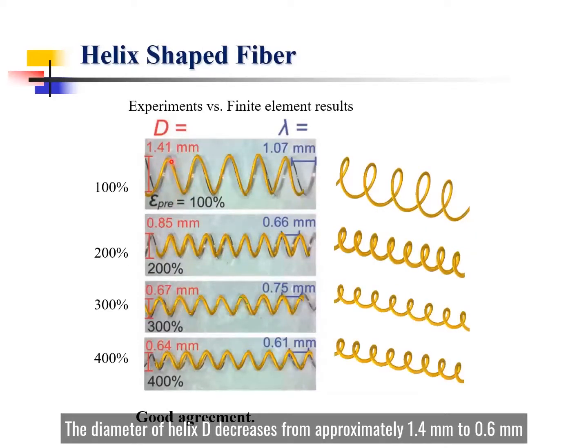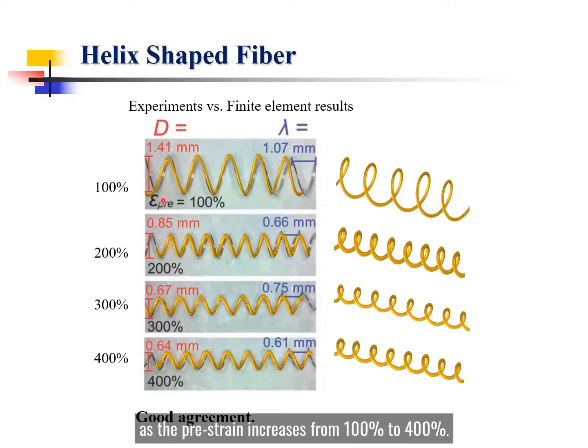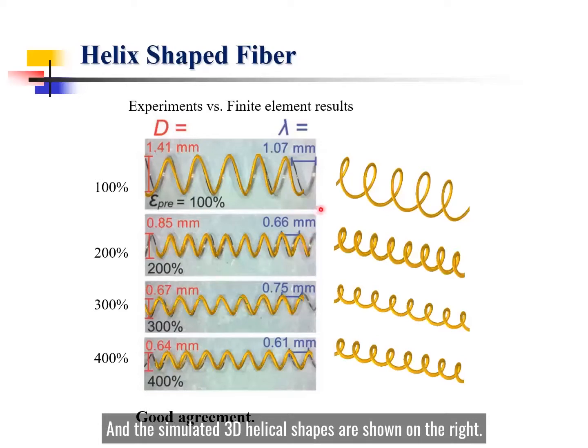The diameter of the helix D decreased from approximately 1.4 mm to 0.6 mm as the pre-strain increased from 100% to 400%. The experiment results agree very well with the simulation, and the simulated 3D helical shapes are shown on the right.